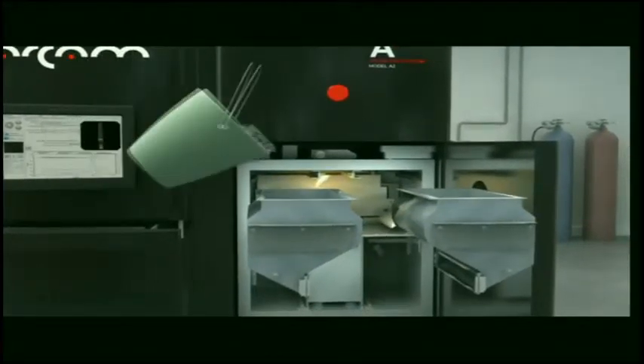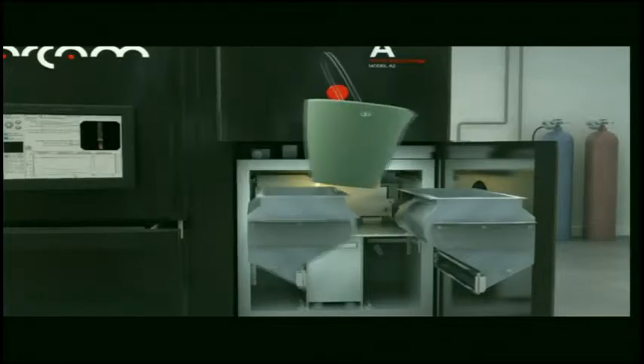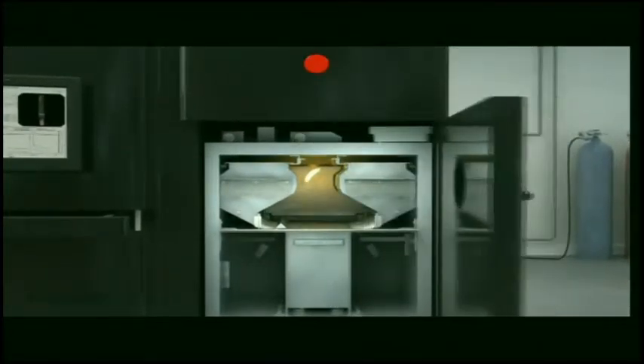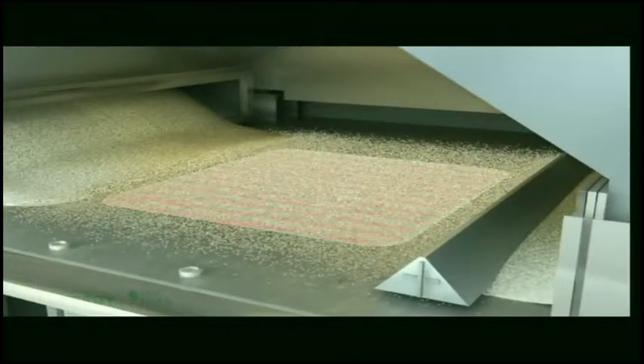We fill those, let's say, with titanium in this case. So we fill up the material dispense areas. We close the door. The electron beam works under vacuum. So then we pull vacuum. That helps us on elimination of oxygen, et cetera. And then the first layer gets swept over, and we preheat every layer.